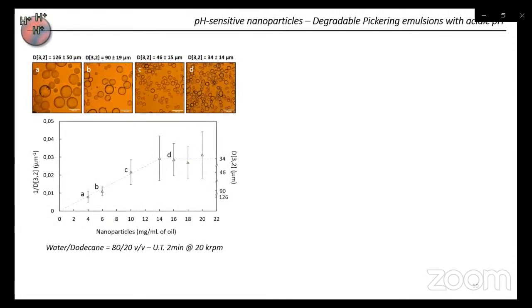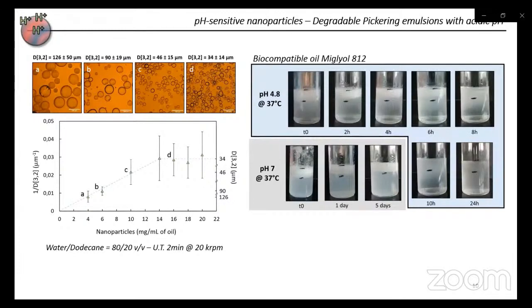Now, moving on to the results we obtained with the pH-sensitive system. With these nanoparticles, we also stabilized Pickering emulsions, and we showed that we also have the limited coalescence phenomenon. And we did some destabilization attempts using acidic pH. The acetal moieties which are on the dextran chains can be hydrolyzed, and this, as with the photosensitive system, leads to the hydrolysis of the nanoparticles. Nanoparticles are degraded so that the droplets of oil can merge together, and we can observe a macroscopic diminution of the emulsion within 24 hours, whereas with the sample at neutral pH, no destabilization occurred after 5 days.